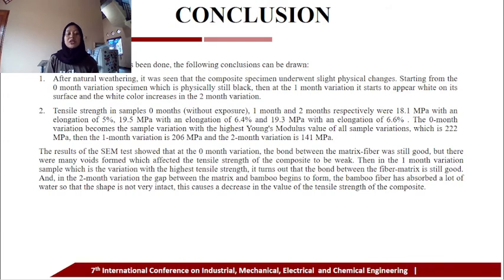And then the conclusion from the research that has been done. The following conclusions can be drawn. First, after natural weathering, it was seen that the composite specimens underwent slight physical change, starting from the 0-month variation specimen, which is physically still black. Then after a month of variation, it starts to appear white on its surface, and then the white color increases in the 2-month variation.